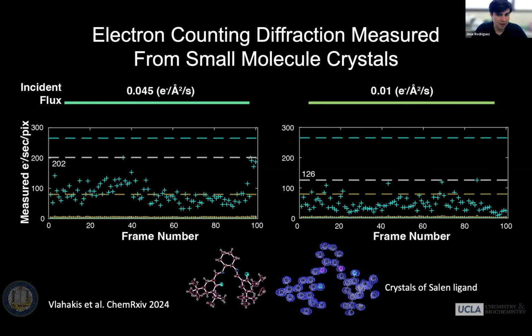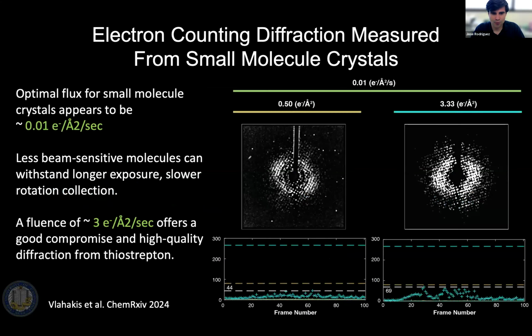that when bright reflections come into the field of view or come into reflection condition, then you can end up with some momentary reflections appearing on the detector that are very bright and might exceed your thresholds for counting. Of course, what you can do as an alternative is basically crank down the dose and spread that dose over a broader region of reciprocal space. And so you can basically slowly rotate your crystals, slow down the experiment a bit, bring your dose down, and still accurately count from some of these molecules. Even if they diffract very well, you can maintain the counts to values that are lower than those anticipated for essentially undercounting quite a bit.